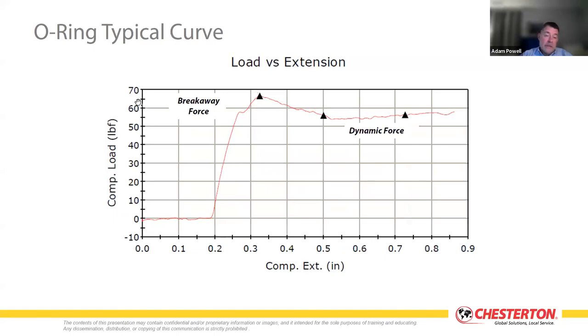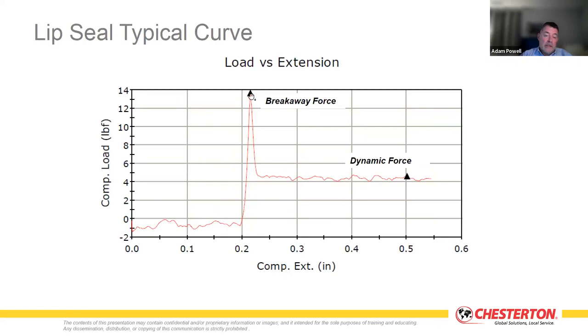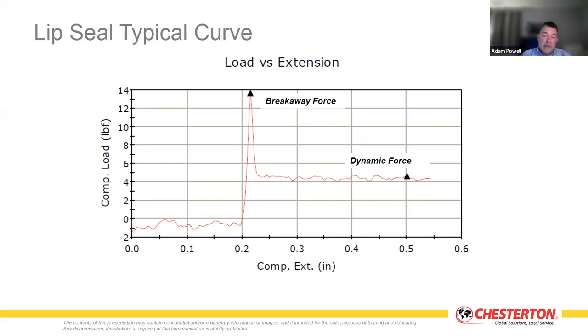So we're here, sorry, this is in imperial units, but 65 pounds force. And with the lip seal, it's 14 pounds force. So that loading that's occurring on the lip is significantly less. And then in the dynamic range, it's lower again, whereas with the O-ring, it remained fairly high, up in the 50s. So what that shows is that the breakaway force is less. Consequently, the sealing lip is being exposed to lower forces. So that material in the sealing lip is under less force, less wear on the equipment, less wear of the seal, longer life, and in the dynamic range, even lower again.